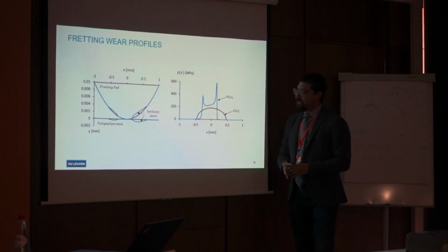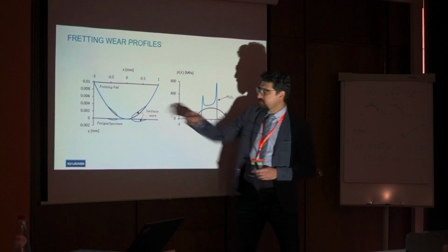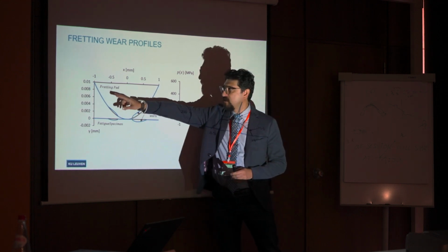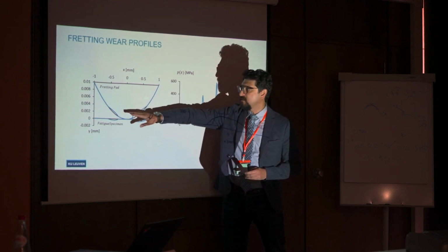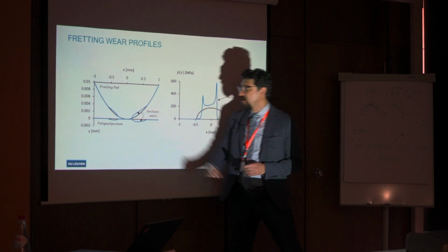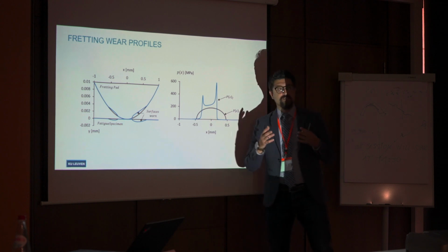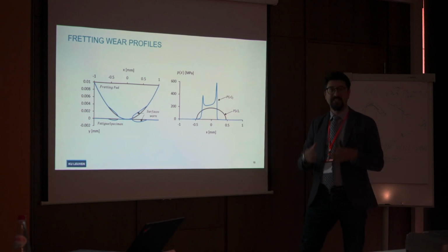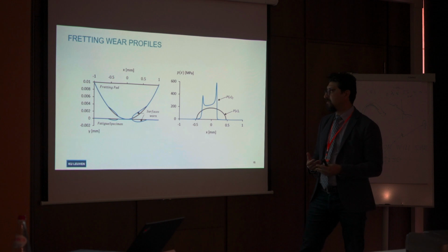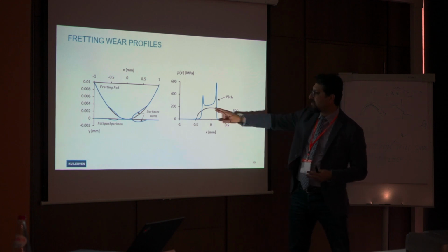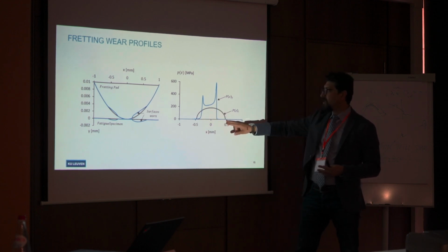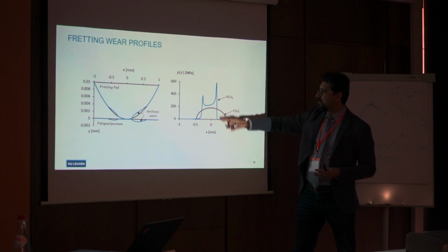Here, what you see is the worn profile. So as I said, we try to simulate the wear on, let's say, this pad and also on the fatigue specimen, and that has a big influence on the stress distribution at the contact interface, even if we have a partial slip region. So what you see here is the first cycle without any wear, and then this is the last cycle with the wear.